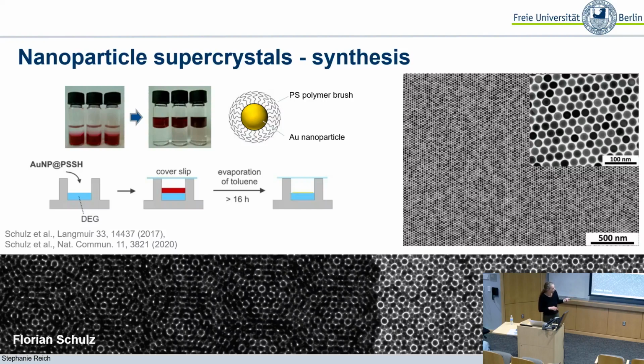He was also able to ensure an extremely high uniformity of the gold nanoparticles. So this is a TEM picture, and you can see that they're all nice and round and exactly the same size. And the ligand also promotes a hexagonal order when you dry these gold nanoparticles on a liquid surface.